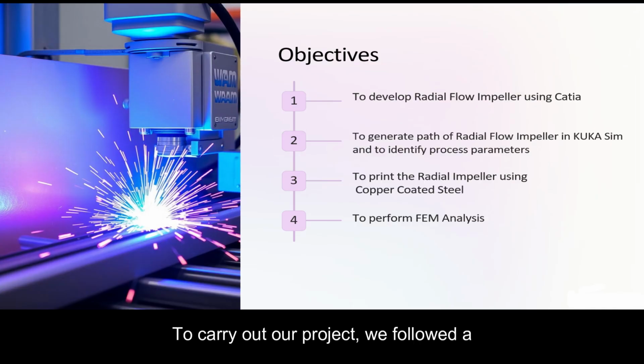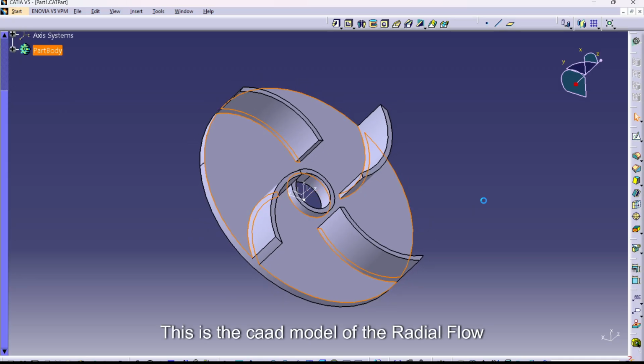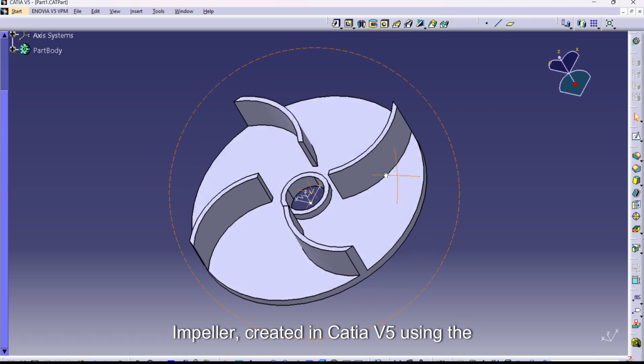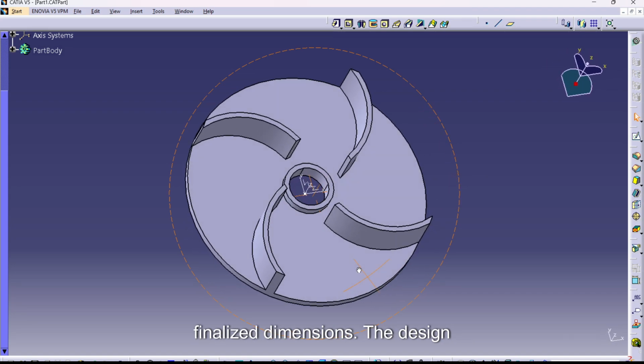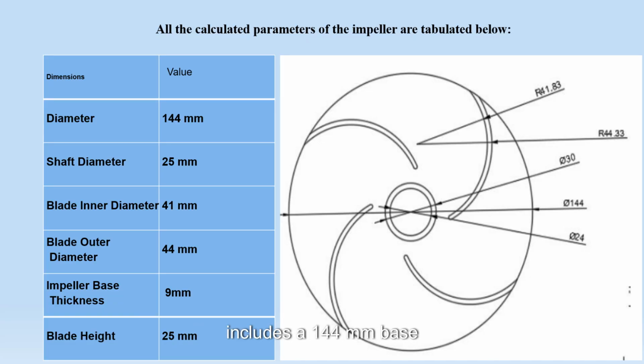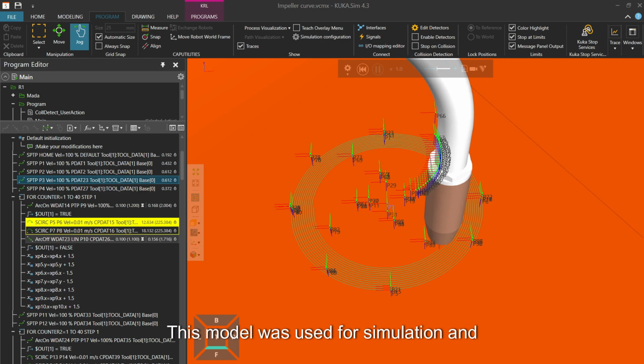To carry out our project, we followed a structured methodology combining CAD modeling, simulation, and fabrication. This is the CAD model of the radial flow impeller, created in CATIA V5 using the finalized dimensions. The design includes a 144 mm base diameter, 25 mm shaft, 41 mm inner and 44 mm outer blade diameters, 9 mm base thickness, and 25 mm blade height. This model was used for simulation and fabrication in the next phases.